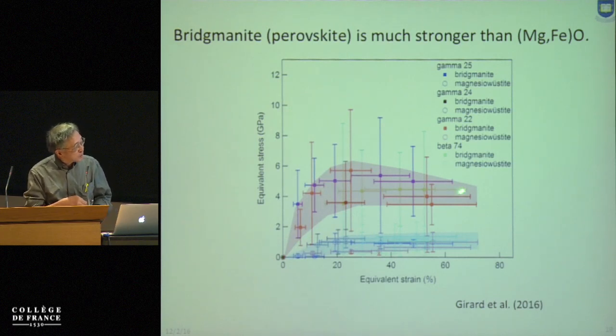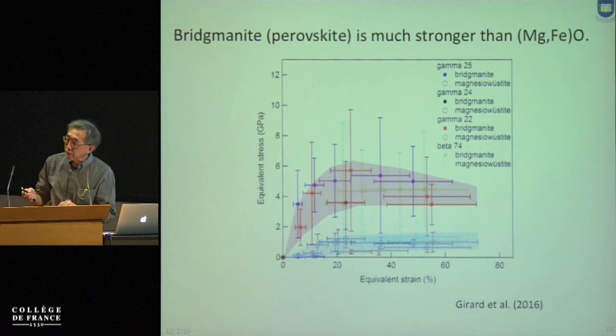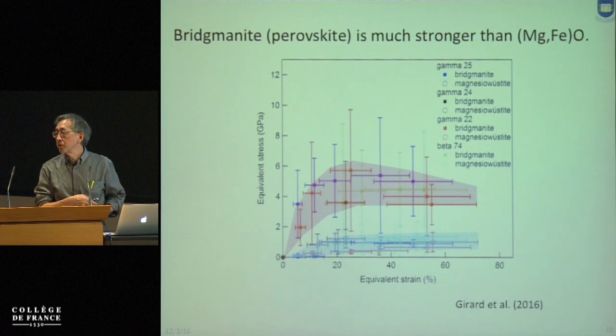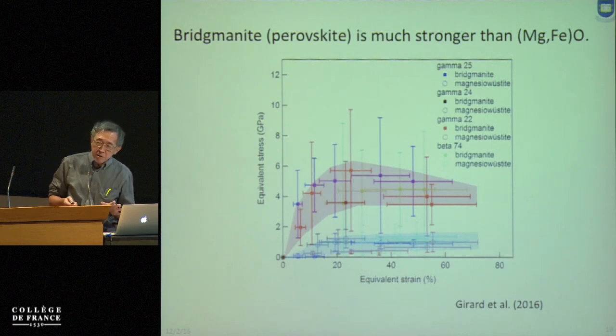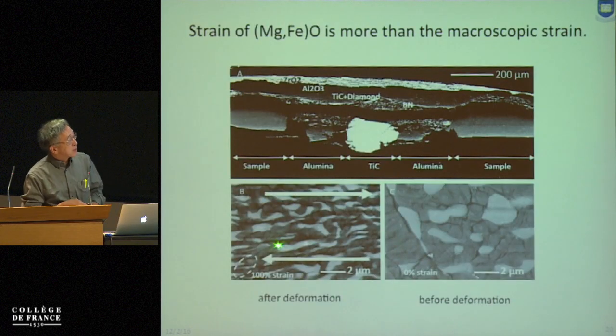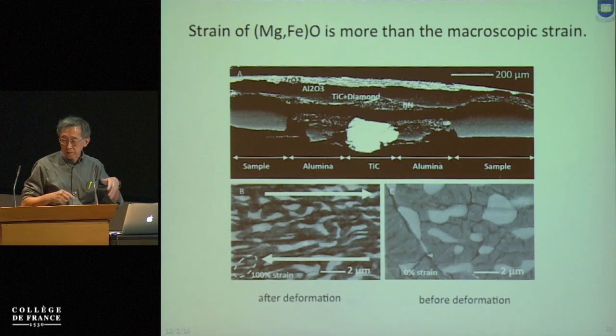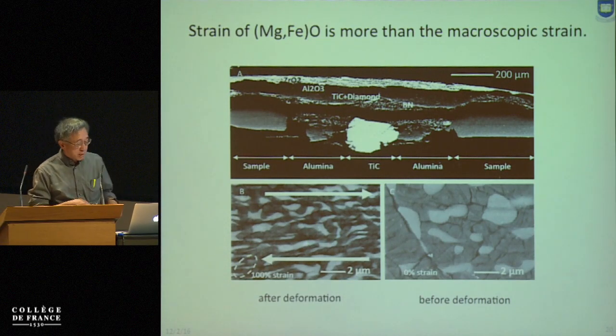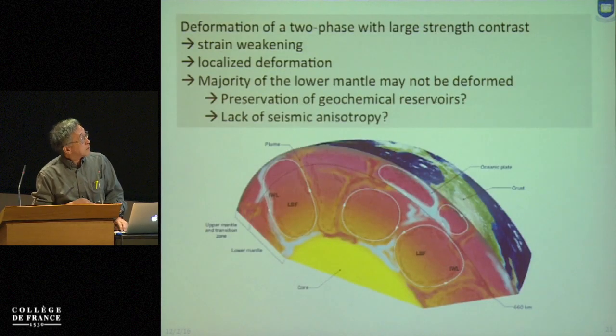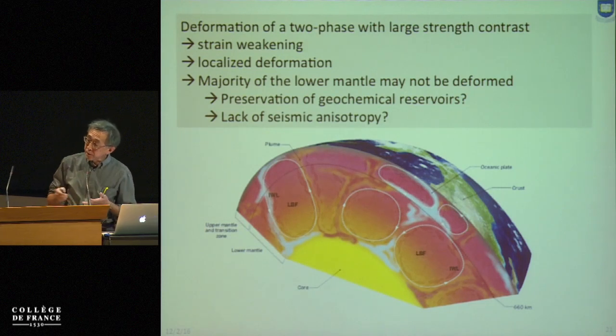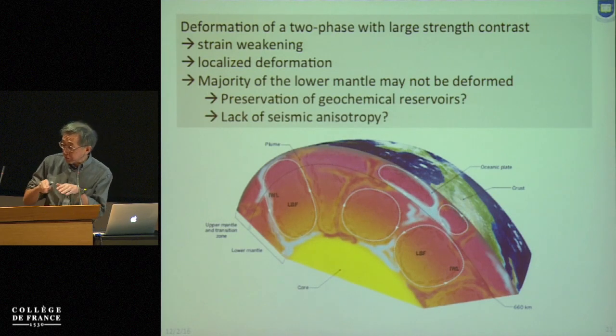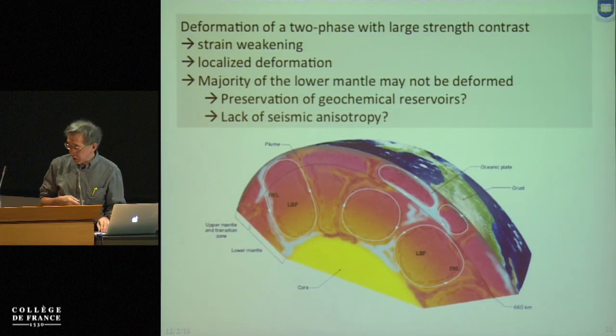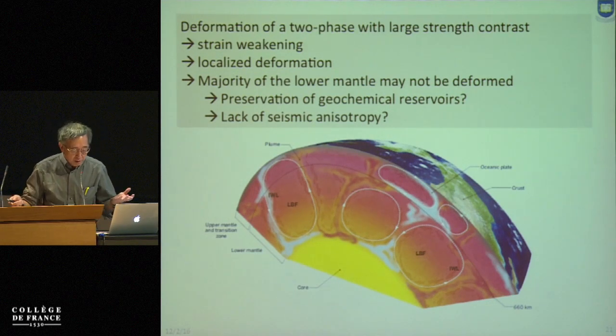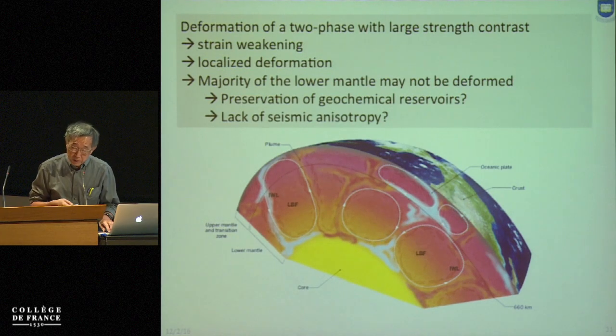And you can see some hint of rheological weakening. The main point is that if you have 70% of very strong material mixed with 20 or 30% of weak material, at least theoretically, you can speculate that there might be some process of shear weakening. Okay? And this is the deformation microstructure. Before deformation, it is mostly isotropic structure, but after torsion, you can see a substantial amount of strain in your sample. And then you might speculate that if the deformation occurs in the weaker phase, you might expect the deformation to be very much localized. This is a potential explanation for geochemical reservoirs, why they survive so much. And this might be able to explain the lack of seismic anisotropy in the majority of the lower mantle.